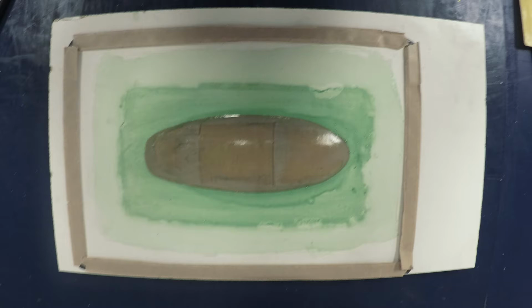This is a water-soluble, plastic-like coating that can be easily applied and cleaned off when finished. However, the reason why PVA was chosen in this case is the lack of strong chemicals in the substance. Due to the 3D printed surface, any chemicals in the other release agents would most likely affect the plastic and negatively affect our finished surface.